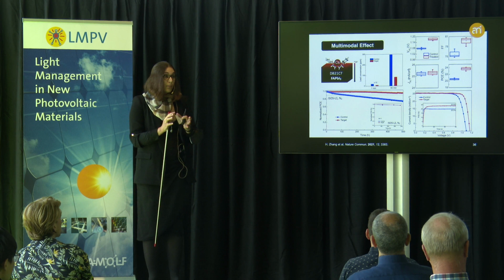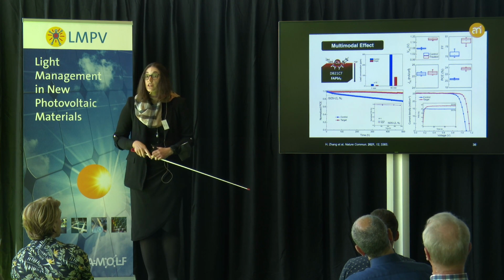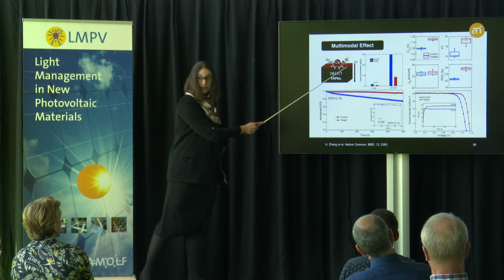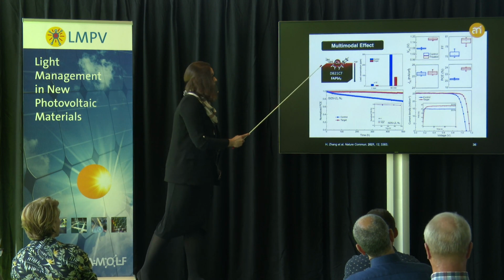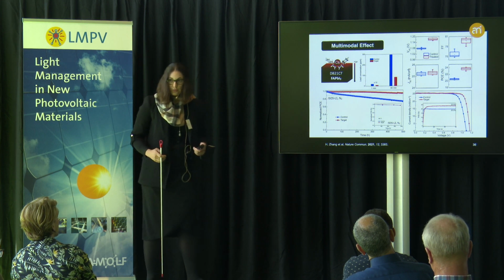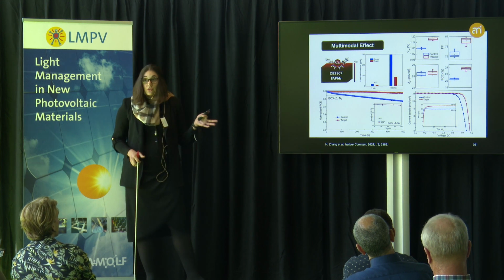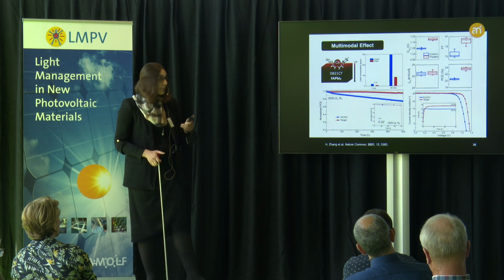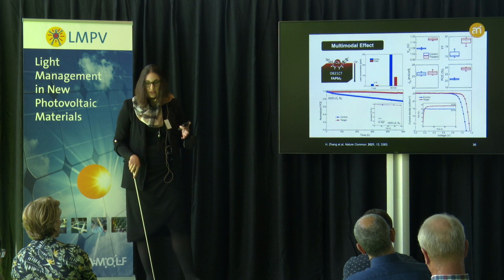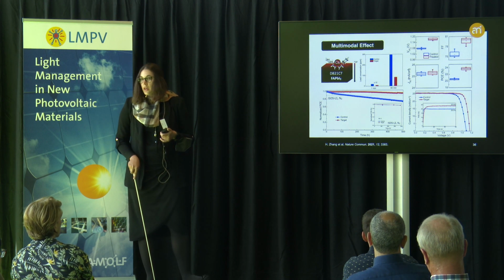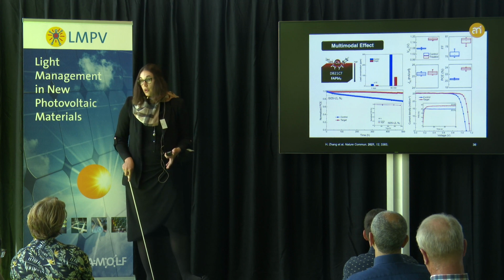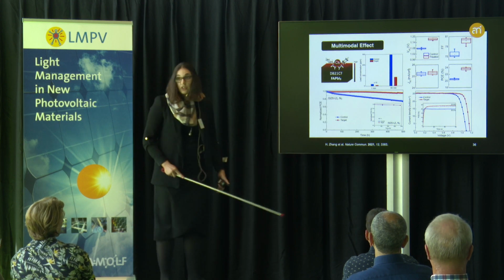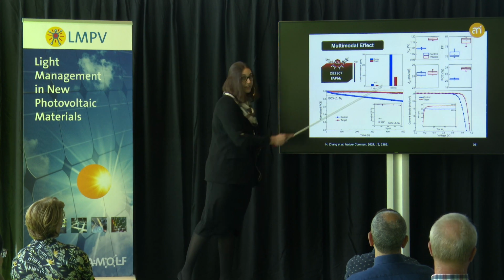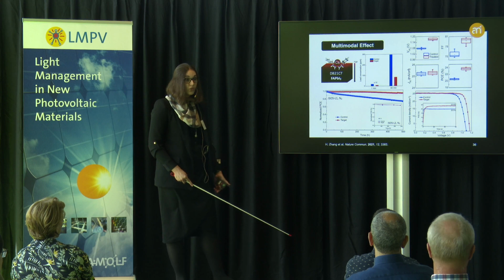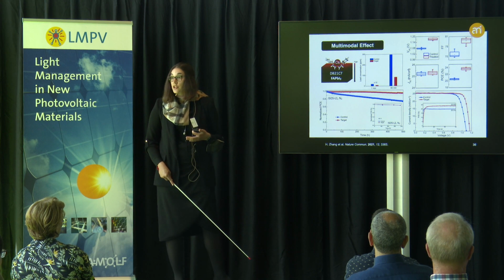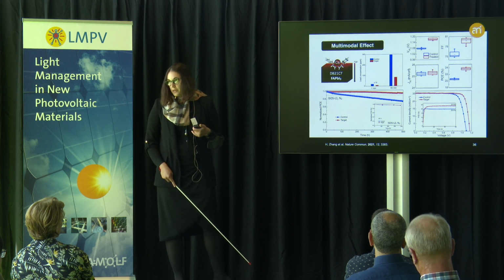Highlighting the importance of these multimodal host-guest complexation strategies relying on a synergy between these hosts binding these defects at the interface, the guest stabilizing the bulk perovskite, and the host-guest complex triggering this in the first place. One of the motivations for me to bring this example to your attention is that these strategies are in this case not only relevant for the photovoltaic performances or stabilities, but also potentially increasing the sustainability of these technologies, as when we would immerse these solar cells in water, we could see that the release of lead ions is substantially reduced, suggesting perhaps that we could rely on some of these strategies to suppress their negative environmental impact.